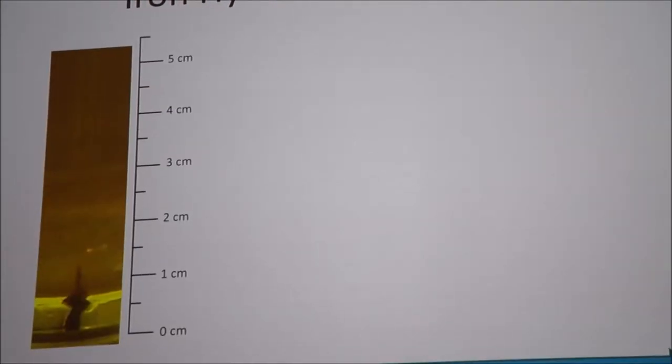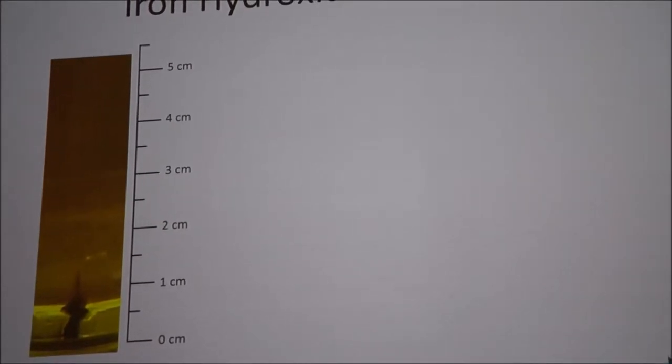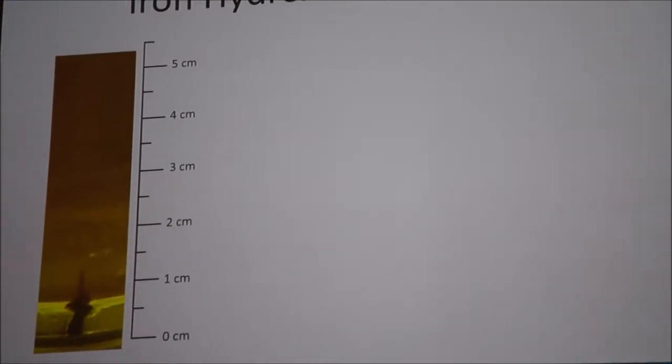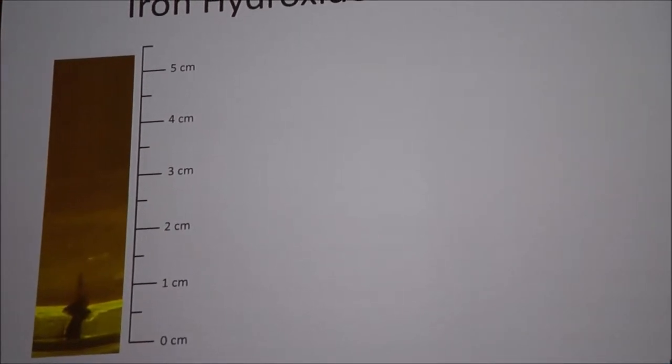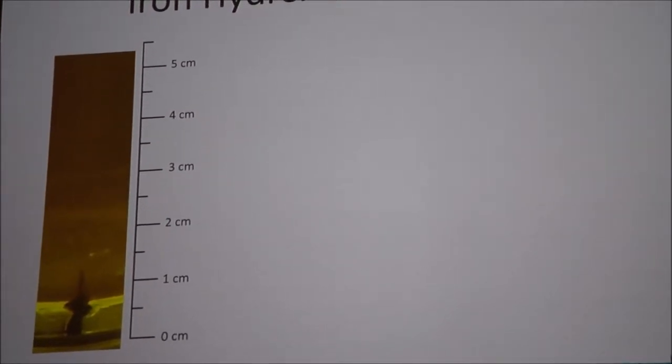Initially we get a little stub. The way these things grow is we get this bursting mechanism where pressure from the syringe is coming up into the chimney and it causes it to rupture at the top. Then fluid coming up can precipitate out and it bursts and solidifies repeatedly to make a stalk. If there's any kind of weak spot in the chimney wall, that spot can rupture too and we get branches.